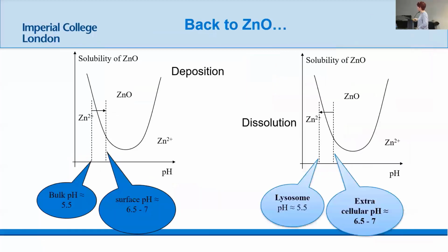Okay. Last thing I want to do is just go back to zinc oxide. I talked about going from bulk to surface and precipitating out all those beautiful zinc oxide nanostructures. Of course, the corollary of that is if you go backwards, you'll dissolve the zinc oxide. I told you that a little bit with the formation of the tubes. But actually, this pH window here, where zinc oxide does this, is biologically really relevant.